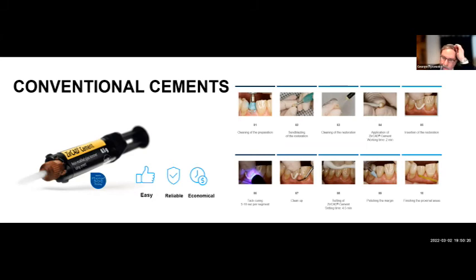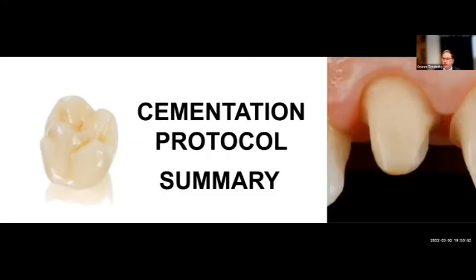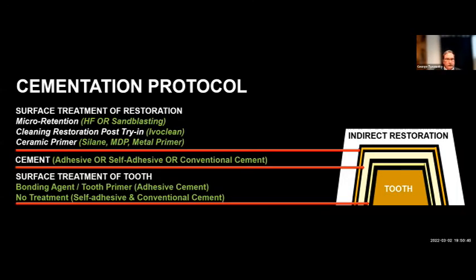So we go from 30s for total adhesive, we go for 15 roughly for self-adhesive, and the resin ionomers have a small bond, but it's between 4 and 6. So basically a light adhesive reaction on that type of area. So summarizing our protocols, again, very importantly is to understand what material we're using, how to use it accordingly, priming the restoration, priming the tooth structure, and relating it to the material we're using with the appropriate cement to lute them in and bond them in together to have a very good seal on the final restorations.